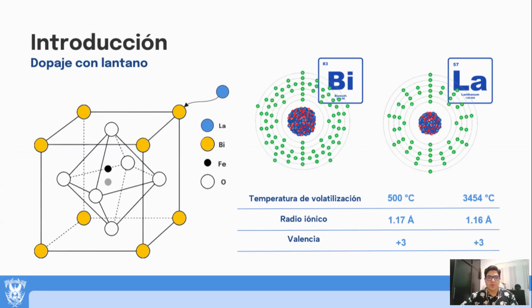However, its practical implementation has been limited by several technical challenges, including the formation of undesirable secondary phases like bismuth iron oxide due to bismuth volatility during synthesis processes, as well as high electrical conductivity associated with point defects in the crystal lattice and the presence of mixed iron oxidation states. These issues generate high leakage currents that impair ferroelectric performance and hinder electrical polarization in real devices.